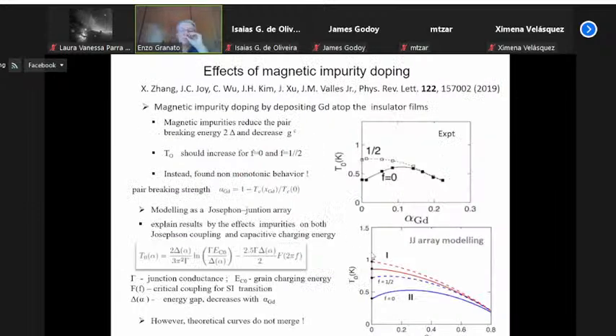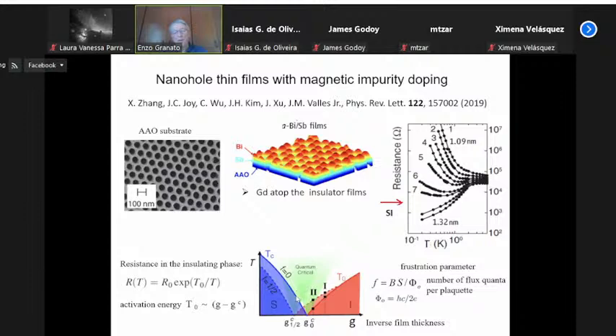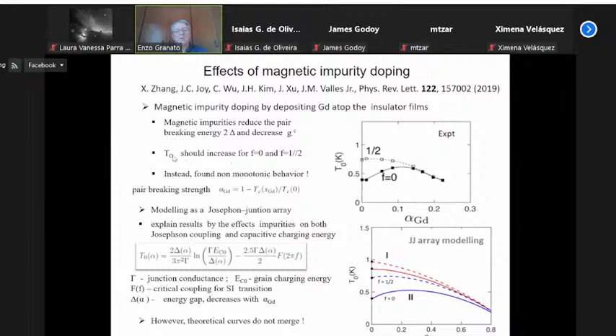Instead, you find something different. This is what they find experimentally by doping the system with magnetic impurities, gadolinium here, during the growth process. Magnetic impurities reduce the pair-breaking energy of the superconducting gap, and therefore should decrease the critical temperature. The effect of magnetic impurity should actually be to move the boundary for the superconductor-insulator transition to the left. So the activation energy should increase both for zero frustration and for 1/2 frustration.